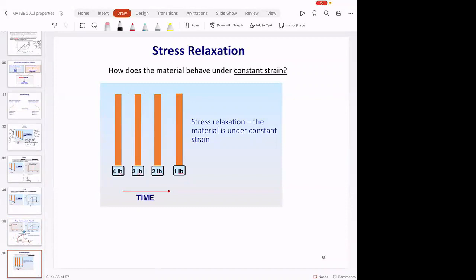All right, stress relaxation. This kind of looks like exactly the same situation, right? But you have to look really closely at this diagram. What this shows is that at constant strain, because the stress is relaxing, so you hold the strain constant. So I'm going to elongate this like a delta L of 20% or something like that. And if I hold that polymer sample at a given elongation, you see the load it can support goes down as a function of time. So in effect, if I'm at a constant deformation and the load or the stress is going down as a function of time, what's happening is my effective modulus is going down, down, down, right? Because modulus is calculated from the slope of the stress strain curve.